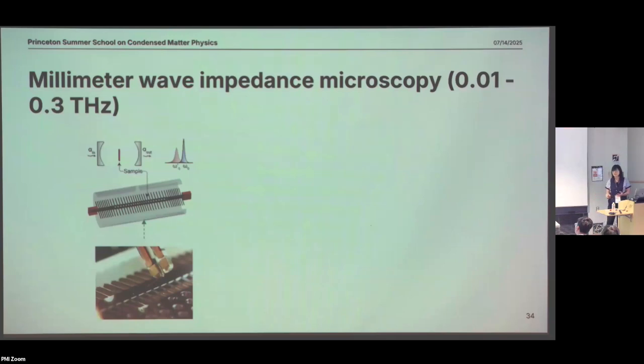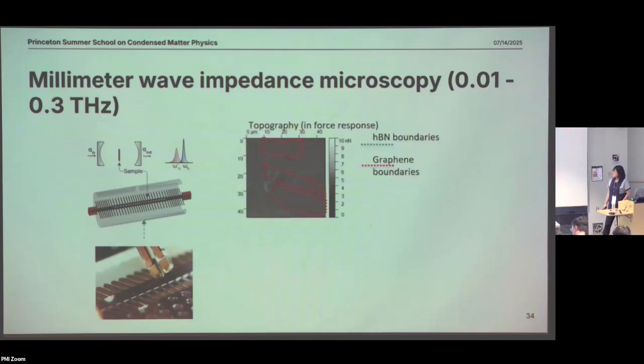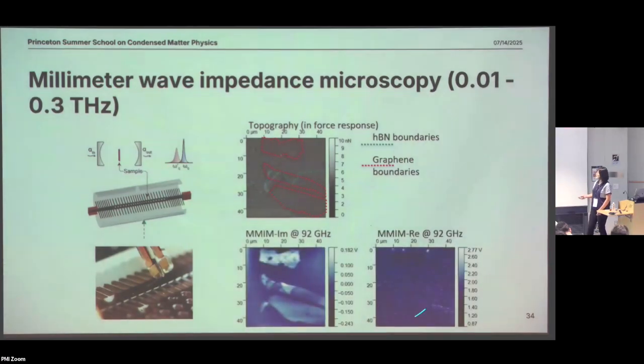But we also wanted to incorporate microscopy into it. So what we did was we put the tip onto a tuning fork, and this is the tip, and we made it really close to this photonic crystal. In this specific case, we didn't etch the holes, but instead this is a waveguide, so it allows a broadband transmission in the millimeter wave region. And here we hover the tip on top of the sample, and that's where the microwave or millimeter wave comes in. And then we use one of the ports to collect the millimeter wave coming out. And that's what we get.